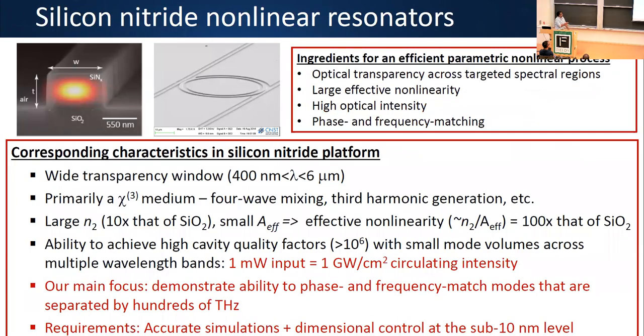What this typically means for us is we use ring resonators, a very common geometry in integrated photonics. The specific material platform we work with is silicon nitride, grown on silicon dioxide on silicon. The main reasons: it's pretty well understood, available in commercial foundries, the refractive index dispersion over wavelength is well characterized, and you can achieve pretty good losses across a broad range of wavelengths. It has a relatively large third-order optical nonlinearity — about 10 times that of glass — and taking into account modal confinement, a pretty strong nonlinearity relative to optical fiber.